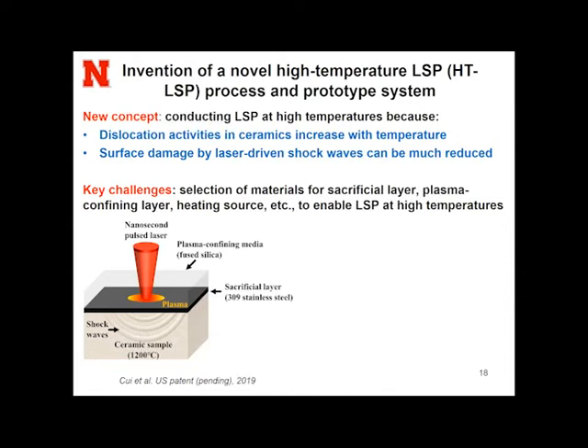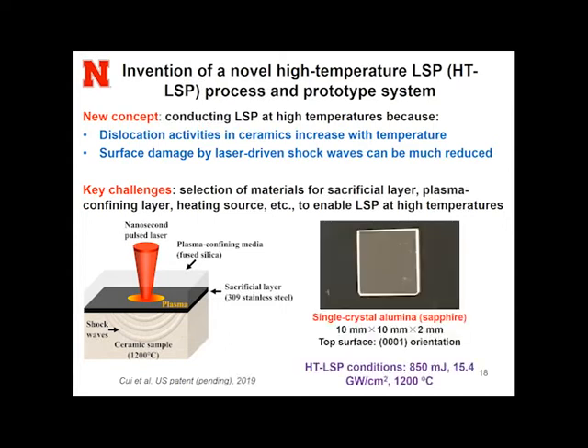So in 2016, we developed this new idea to perform the laser shock peening at high temperature, because we know the ceramic can have a higher dislocation activity at high temperature, and a lot of ceramics have the brittle to ductile transition. For example, alumina, the transition temperature is about 1000 C. So above the transition temperature, ceramic shows much more plasticity and ductility. And also because of the higher ductility at high temperature, the surface damage by the shock wave can be much reduced.